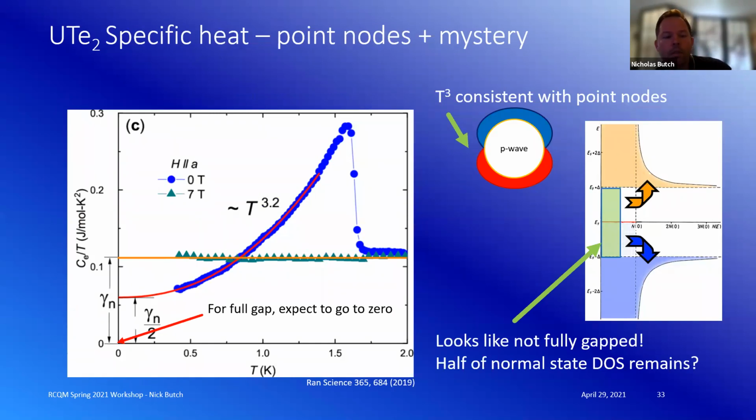So this is old, I'm sorry, maybe I didn't show this before, but here we go. So I showed you the two transitions before I showed you the first one. I apologize for that. This is from the paper, and one thing about it that's easy to read off, and you can take with a grain of salt, is that the temperature dependence doesn't look exponential. So it was already consistent with there being some kind of nodal behavior. But in particular, if one extrapolates to 0, there is always a really large residual term, which is about half of the normal state term.